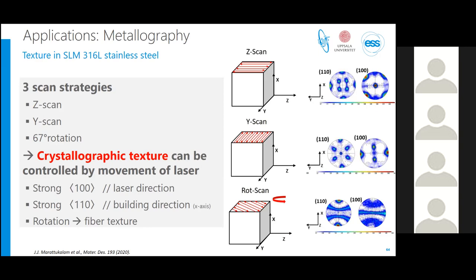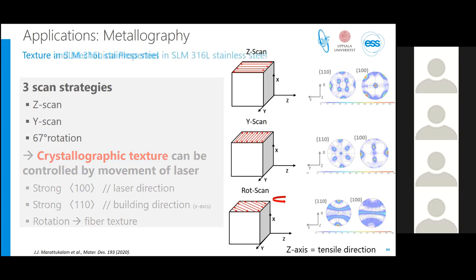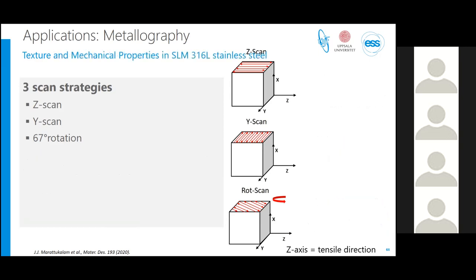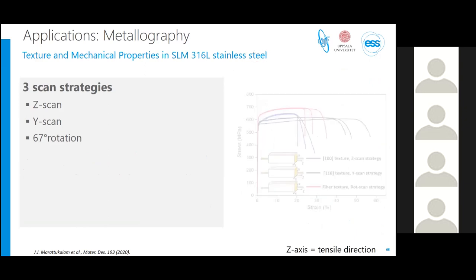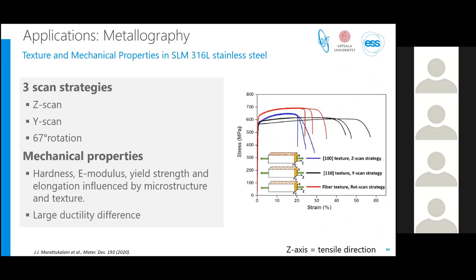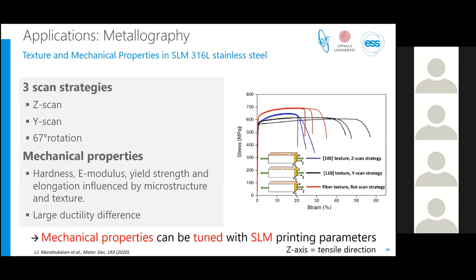What the colleagues did next was tensile testing, where the tensile axis was along the Z direction. They made several tensile samples and tested them. What you see here is a stress strain curve, and you can see that there are large differences in ductility, but also in yield strength. What this basically means is that the mechanical properties can be tuned and are dependent on the SLM printing parameters, or the laser scan strategy in particular.